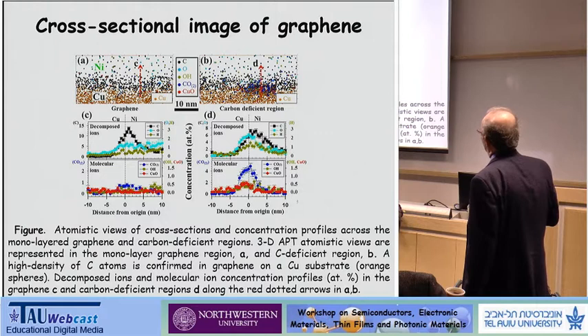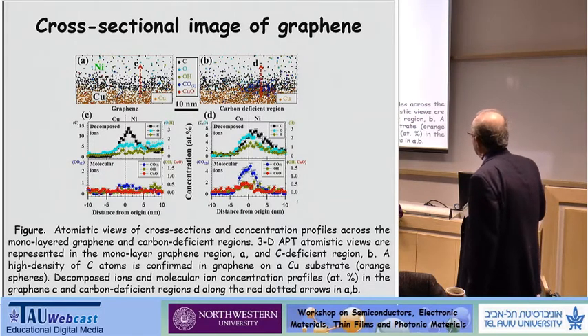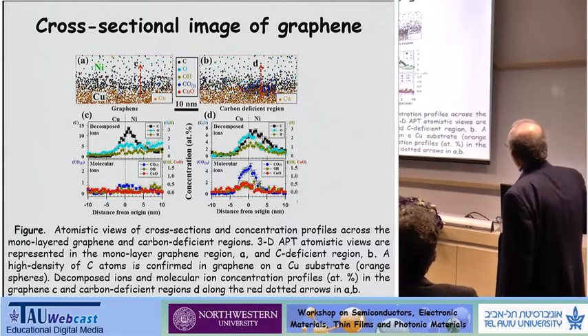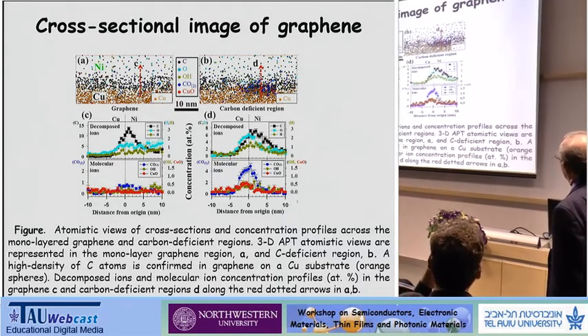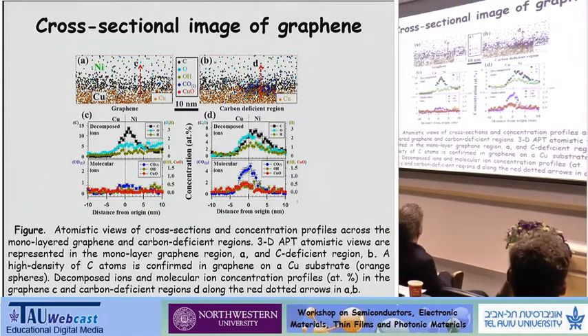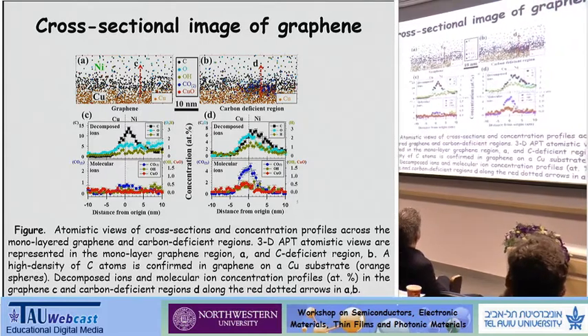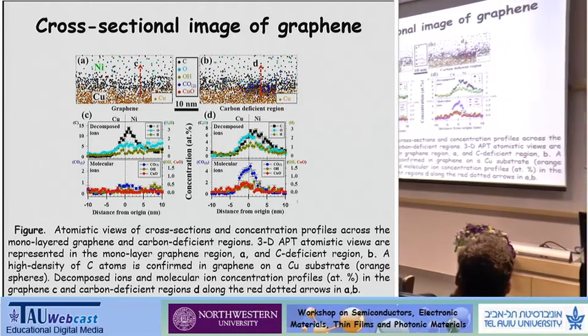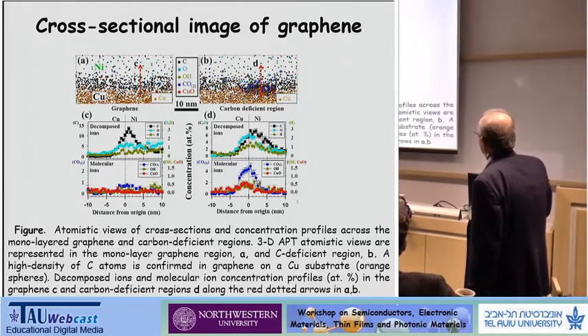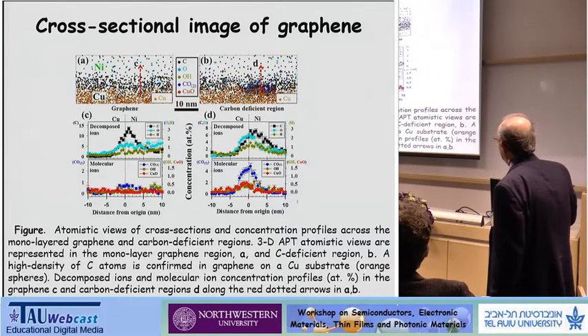Okay, now this slide is a little bit more complicated. This is a cross-section, and you see here nickel, copper, and graphene, and the interface is broadened. And this is in the graphene, and this one over here is a plan view, but in the regions that are carbon deficient. Then if you look down here, you can see concentration profiles in atomic percent. In this first one, these are what we call decomposed ions, so you're seeing carbon, oxygen, and hydrogen. And you can see the biggest peak, as you would expect, is the carbon peak. There's some oxygen also, and a small amount of hydrogen. And over here, you see these molecular ions, but they exist in the pure graphene also, at a lower concentration.